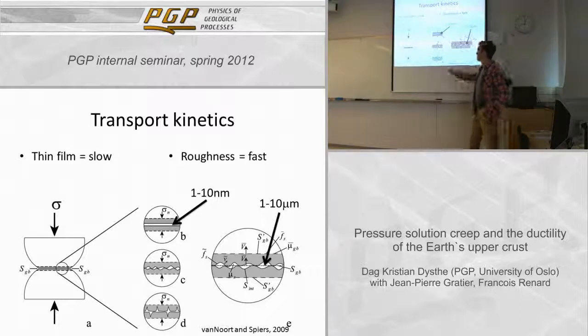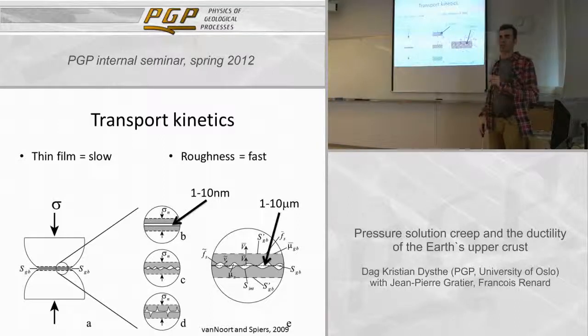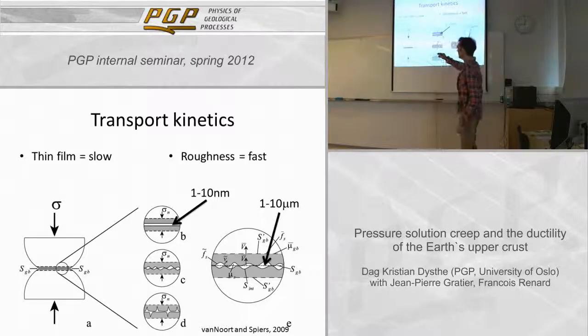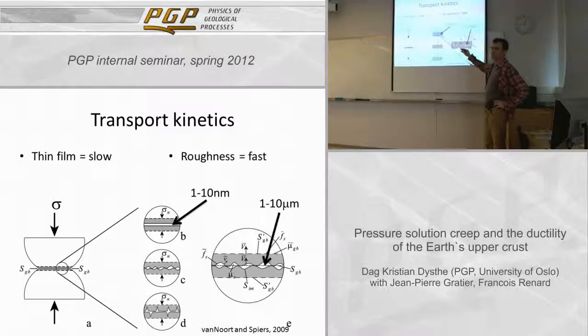On transport kinetics, I've been saying, well, what limits us is that this is a very thin film. It's 1 to maybe as much as 10 nanometer thick film of water, so that you don't have a big cross section to transport your mass out. But observations and theory suggest that this film, this grain boundary region, does not always remain flat. It does become rough or makes what is called an island channel structure, or there are different models for the structure of this, and there have been observations.